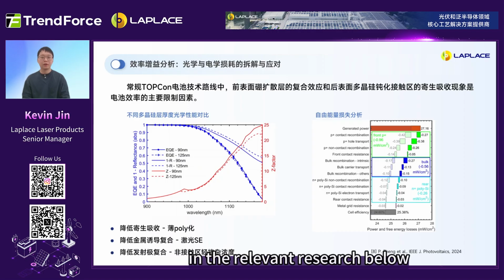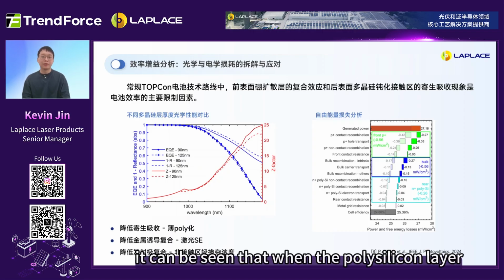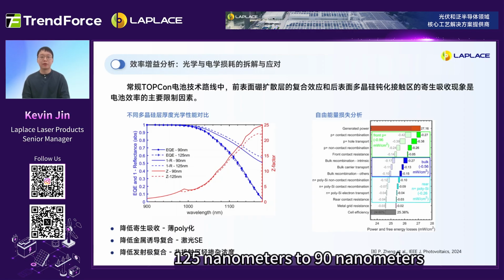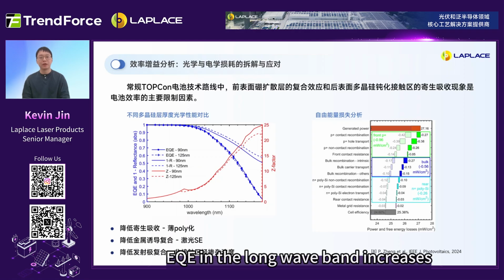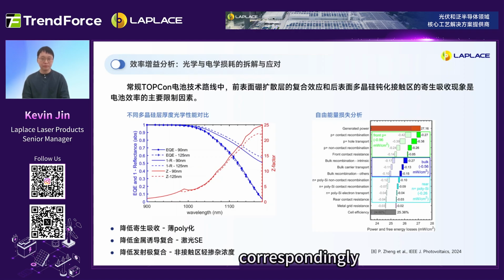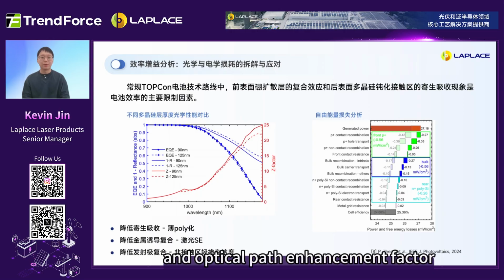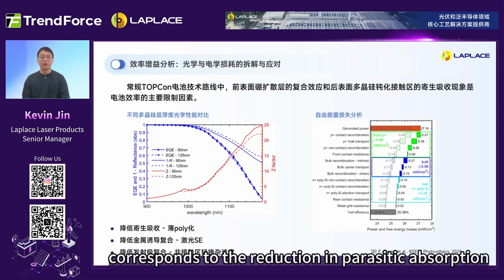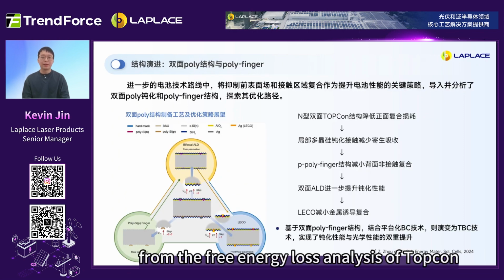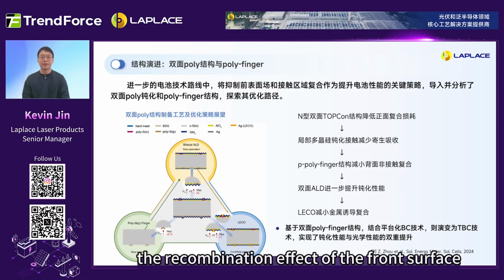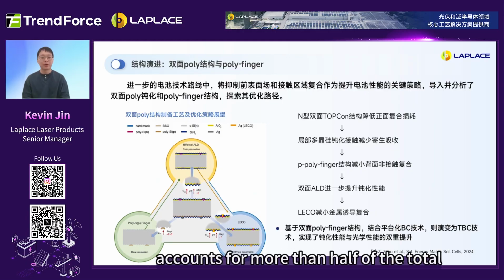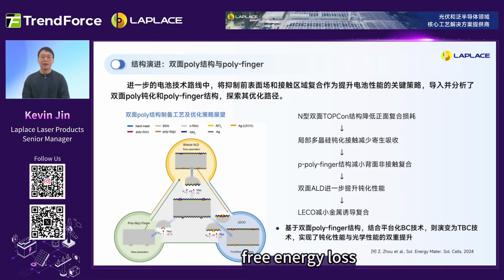In the relevant research below, it can be seen that when the polysilicon layer thickness is reduced from 125 nanometers to 90 nanometers, the external quantum efficiency, EQE, in the long-wave band increases. Correspondingly, the increase in long-wave reflectance and optical path enhancement factor corresponds to the reduction in parasitic absorption. From the free energy loss analysis of TOPCon, the recombination effect of the front surface boron diffusion layer accounts for more than half of the total free energy loss, making it the main constraint.